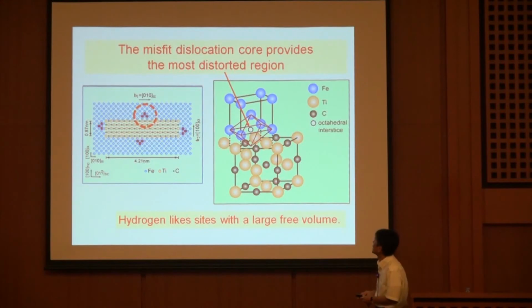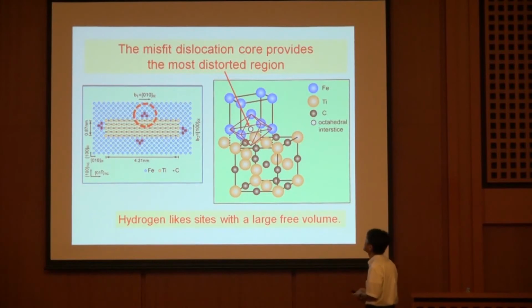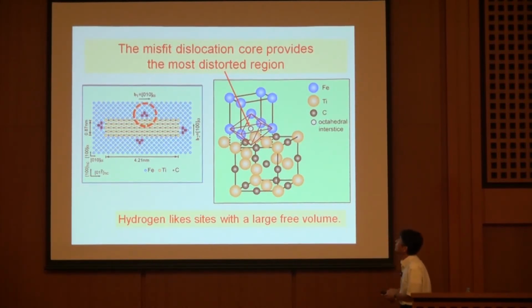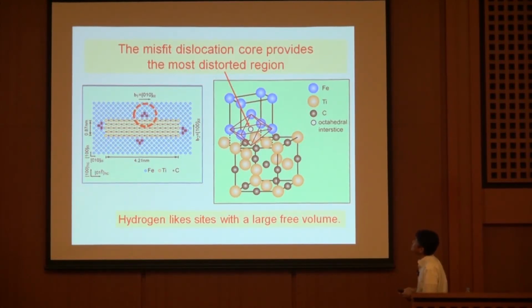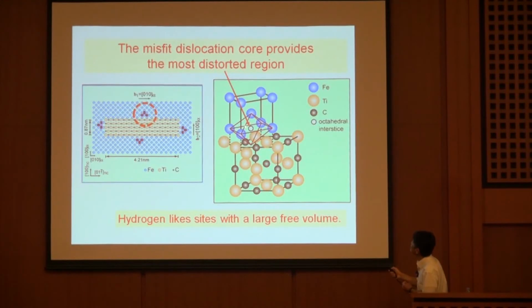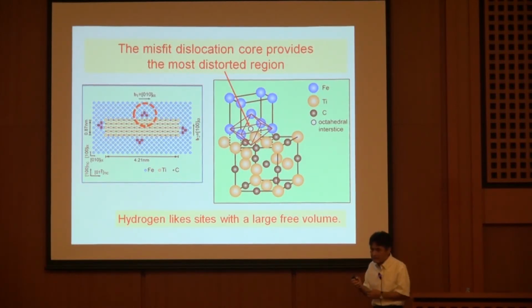Please look at your atomic configuration around the misfit dislocation at the interface. You can find the large distorted region along the misfit dislocation core like this. This is essentially the octahedral interstitial site here. So this is the free volume, large free volume, then hydrogen likes it, because